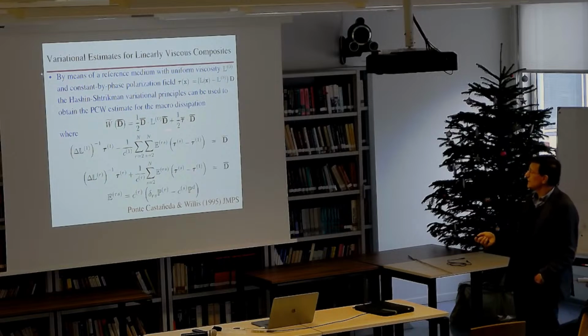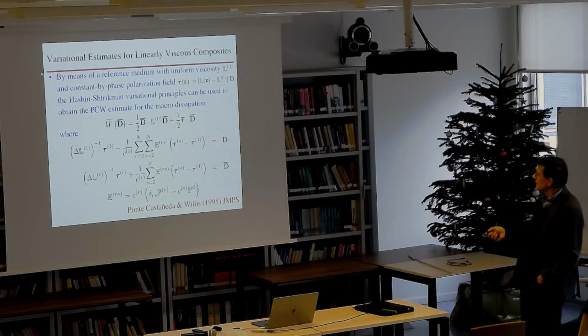I don't have time to go through all the details, but now I'm working with the dual formulation in terms of the dissipation potential. So W tilde is a function of the rate of deformation tensor, D bar, I called it epsilon in the previous slides. Now it's rate of deformation tensor D bar, and it has this term that is quadratic on some reference medium, uniform reference medium, L naught, the microscopic strain rate, of course, and then these equations that describe the polarization fields in the phases of this linear composite.